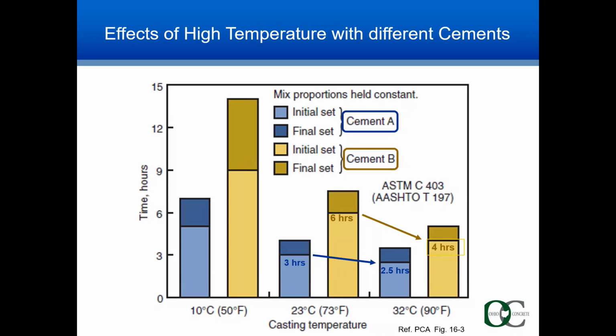As a general rule of thumb, the concrete set time changes about 33% for every 10-degree change in the initial concrete temperature. Different cements behave differently. Here, cement A is in blue and cement B is in gold. The chart shows that as concrete temperature increases from 73 to 90 degrees, the concrete set time is reduced by a half hour with cement A or by 2 hours with cement B.